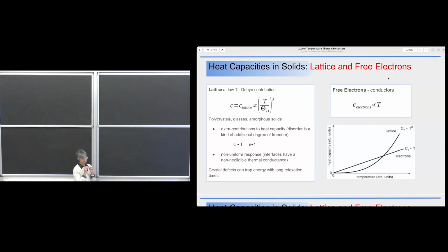It's not true for microcalorimeters, those used for the beta decay studies, for the measurement of the neutrino mass using beta decays, because they are very small, they have a heat capacity that is very small. You can tune the conductance toward the heat bath in order to avoid too long decay time in the signal. But in the case of the thermal detectors using large absorbers, decay times are quite long.